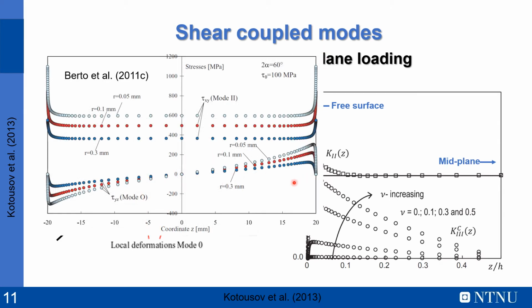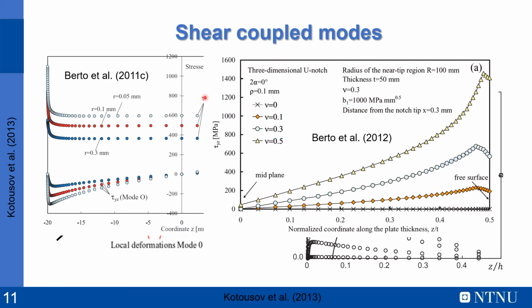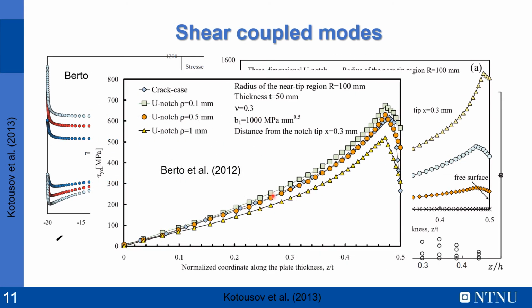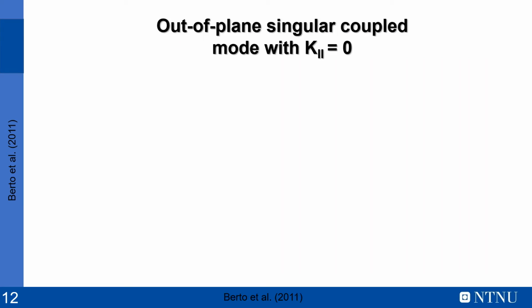So other works confirm these numerical results for cracks and V-notches, as shown here. But both for cracks and V-notches, the existence of the induced mode, even when the primary stress intensity factor K2 is equal to 0, has been proven.